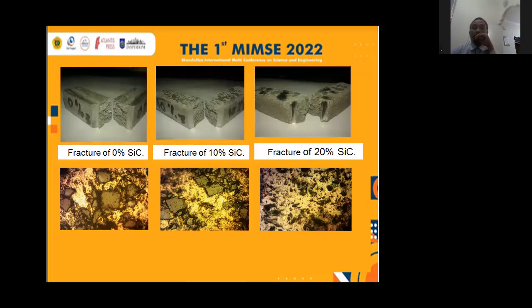For 0% of SiC, we can see clearly here the difference between the fracture of 0% SiC and that with 20% ingredient. And then also the microstructure appearance beneath. We can see here the distinction among the three variations of the SiC ingredients.